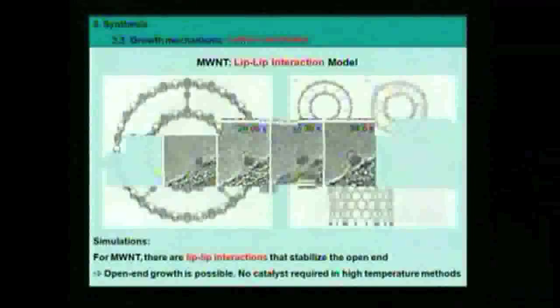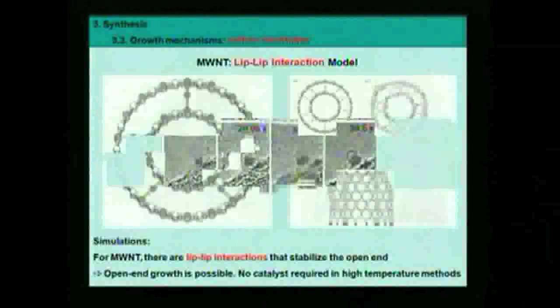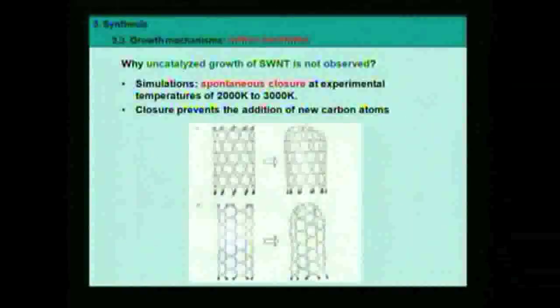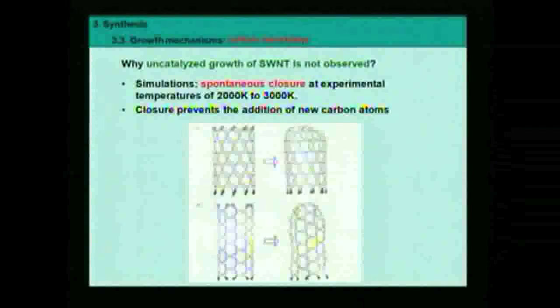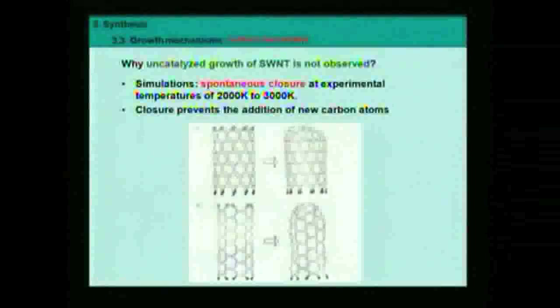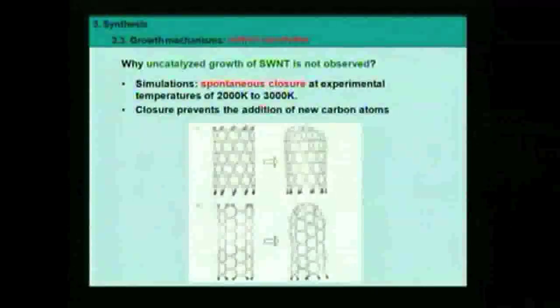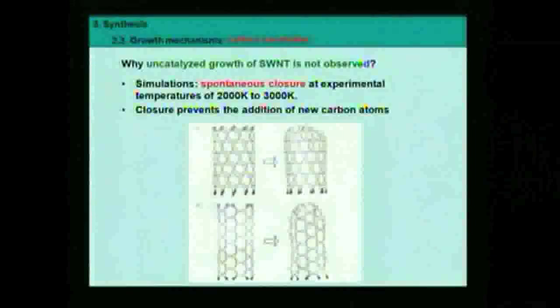Okay, maybe a first thing, which was not expected by people at the beginning, is that the growth starts by forming a cap. It's not an obligation that the cap is formed at first. It may be formed later. For instance, the growth could start, as proposed by many people a few years ago, by an open end, not a closed end. And then later, this open end could close by itself. Here, it's not the case. The first stage is forming a cap. And this cap is used as a seed, as a nucleation seed for growing a longer crystal. Like crystal growth, the cap is central. The cap is the seed of the nanotube that will grow after.